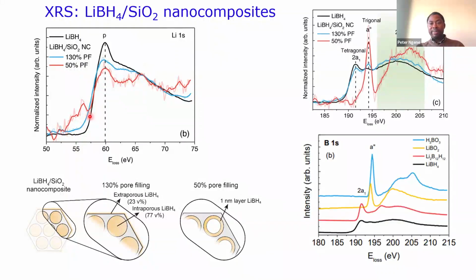So now we do the same thing for the boron. And this is even more remarkable. The boron actually gives us much better results. So here we also start with the 130% pore filling. If you look at the bulk-like lithium borohydride, in this case you can see the bulk-like behavior. If you have 130%, you see that we have a small contribution of what we saw before, the oxidic boron. And then if you go to lower pore filling, which is lower concentration, we see that this bulk-like behavior is gone completely. So we have only this particular feature.